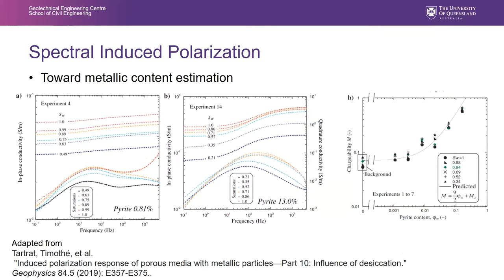So basically, they've been measuring the low frequencies, between millihertz and several kilohertz, of soil with different water content and different pyrite content. On the left, it was a pyrite content of 0.81%, and then a very high pyrite content of 13%. And at the end, they were able to link the chargeability, which is simply the difference between the high frequency conductivity and the low frequency conductivity, to the pyrite content. And this relationship is independent from saturation. So it means that by combining a high frequency method, we could access the water content, and with a low frequency method, we should be able to access the pyrite content. So this is why ultra broadband measurements are fundamental in this kind of application.